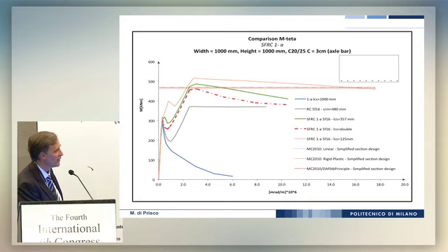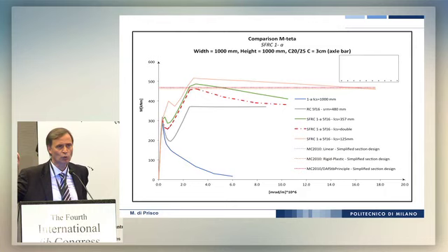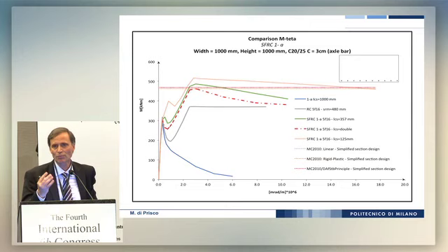That means that fibers give something in bending, but not so much. And also it's very important to see that if I adopt a constant characteristic structural length, which is, for instance, 125 millimeter, you have this value. So we debated a long time in the Eurocode in order to have, in a lot of situations, a constant characteristic structural length, not in the difficult cases, but in the large majority of the cases, in order to simplify as much as possible also the computation.